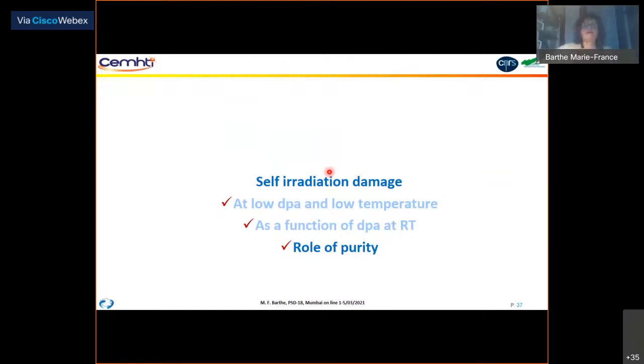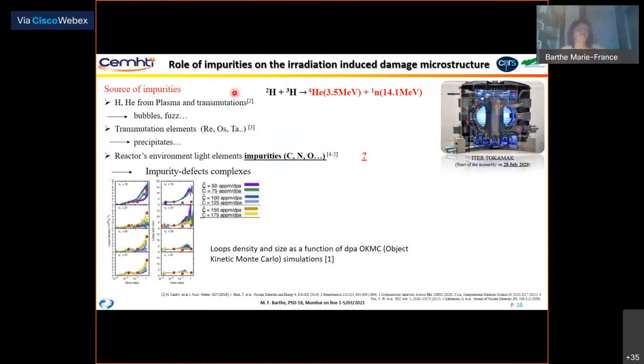So now we can ask what is the role of purity of tungsten material on the damage which is created by irradiation. There are several sources of impurities. One is, of course, the plasma, that means hydrogen and helium, which, as shown, leads to the formation of bubbles or fuzz. There are also transmutation elements from tungsten, which produce rhenium, osmium, and tantalum, and it has been shown that they create some precipitates in the material.